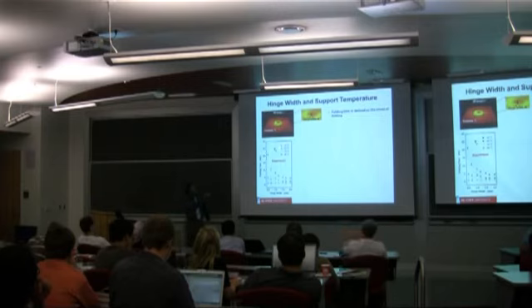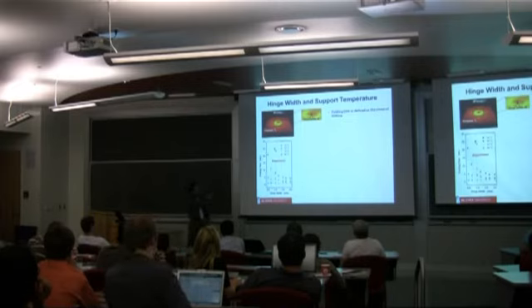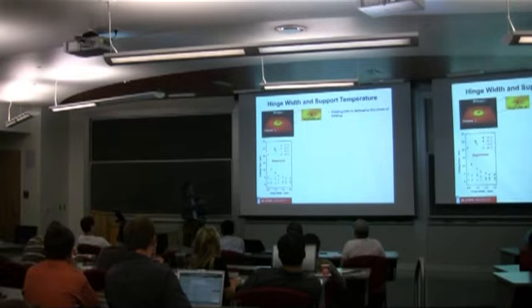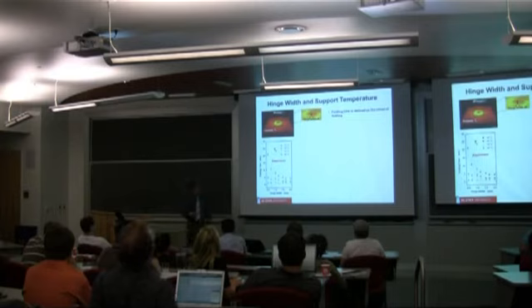The other thing we varied was the hot plate temperature. And let's look at the two extremes. If you start at room temperature, bad things, well, not bad things happen, but it just doesn't work as well. It takes a longer time to fold, and you see big error bars on this plot. If you start at 90 degrees, which is very near the glass transition temperature of 100, it folds within about a second.